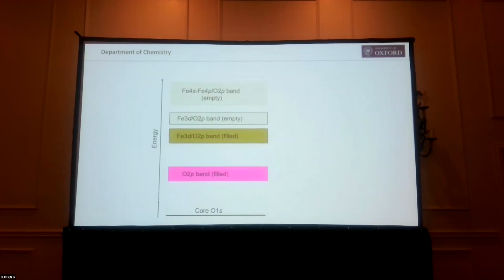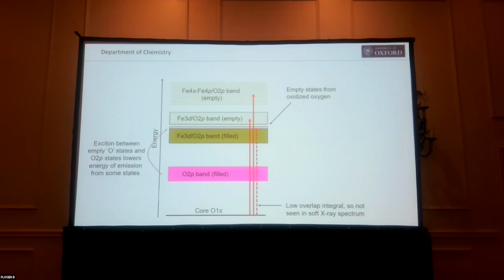And it turns out, if you look at this system, we can think, well, where would the oxygen hole be? Well, the empty state is going to be at the top of the valence band. That's where they're going to be. And it turns out, if you've got an empty state here, first of all, you're not going to see them, because what you need is to see in the soft X-ray, you can excite an electron up into that empty state, and it turns out the overlap is really small. That's what we're going to see. But what you can find is an exciton between the empty state and the filled oxygen.